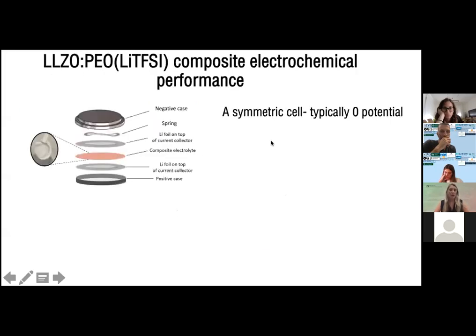And then we wanted to evaluate the electrochemical performance. You can see here how it looked. It's a symmetrical cell. There are two lithium electrodes sandwiching your composite here in pink. Typically in a symmetrical cell, lithium versus lithium, you will get a potential of zero. However, in the presence of the composite and interfaces within it, you can read some voltage, which is your overpotential. And a good composite will give really low overpotential, close to zero.